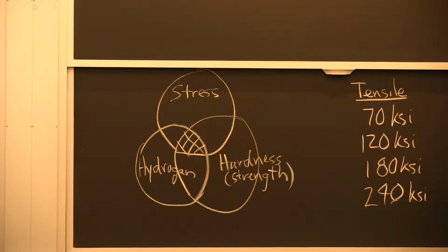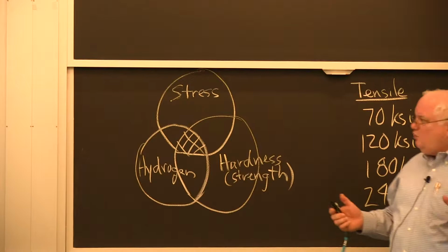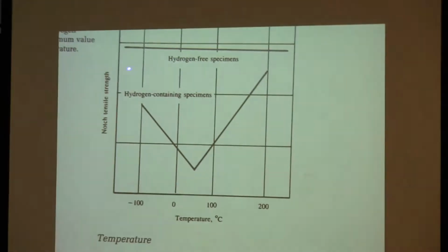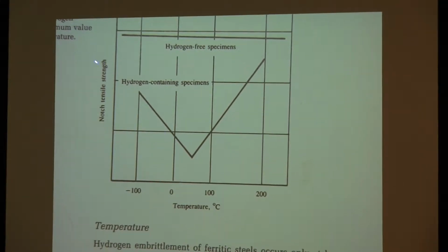It turns out we just live in this perfect world at 20 degrees centigrade. And if I look at the tendency to form a crack, which is notch tensile strength, the lower the notch tensile strength, the easier it is to form a crack. And I look at a hydrogen-free specimen, it will have a fairly high strength. If I look at a hydrogen embrittled specimen, I could have up to 75% reduction in strength because of the hydrogen. So a steel that might have 100 KSI strength might crack at 25 KSI.